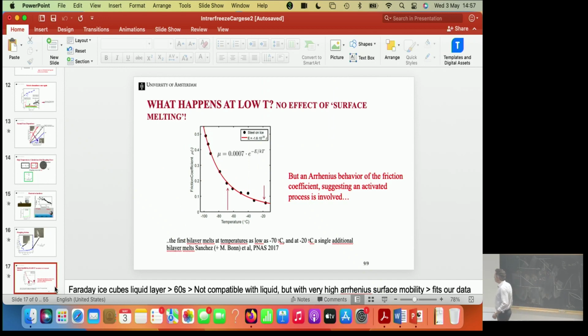And so, what happens then at low temperature? Well, if I cut off the part where we see the plowing, we actually get a very steep dependence of the friction coefficient on temperature. That is completely continuous. That seems to be exponential in the inverse of the temperature. So this suggests an Arrhenius process.